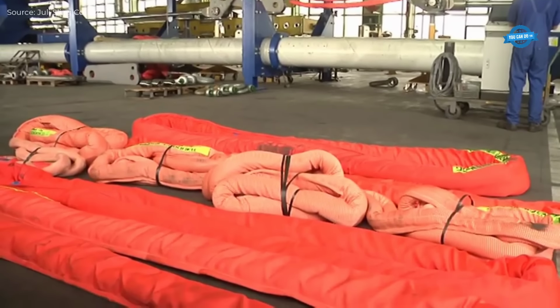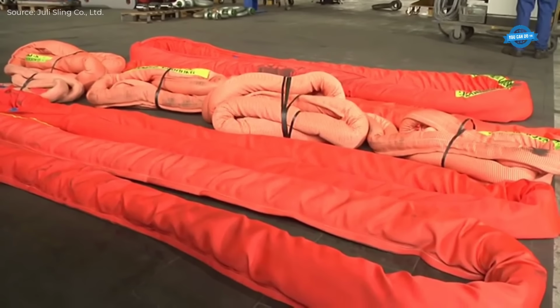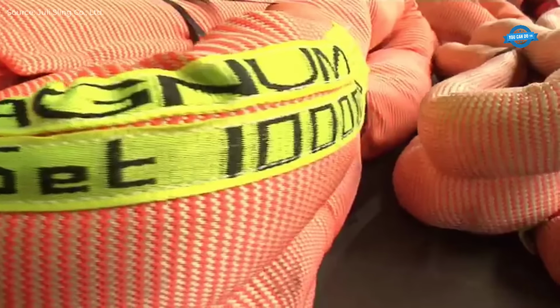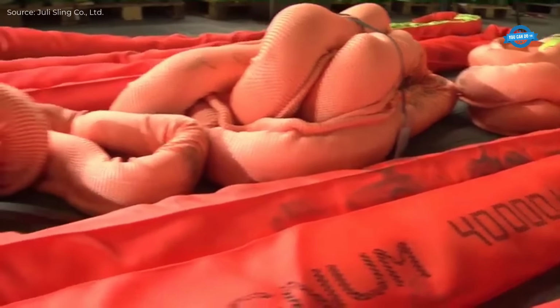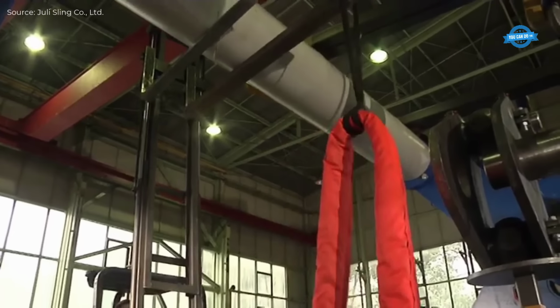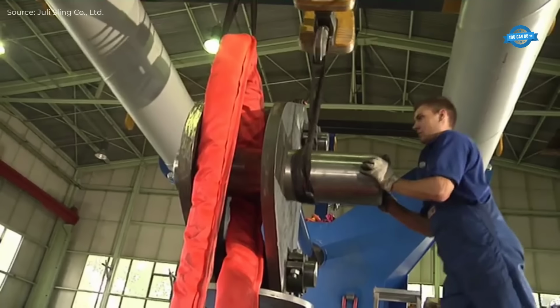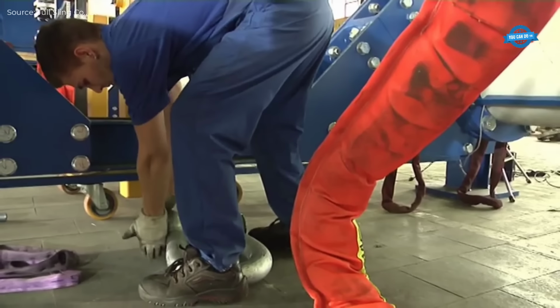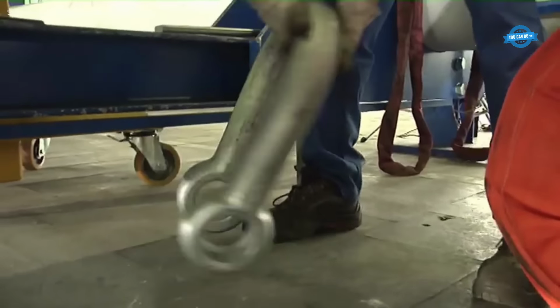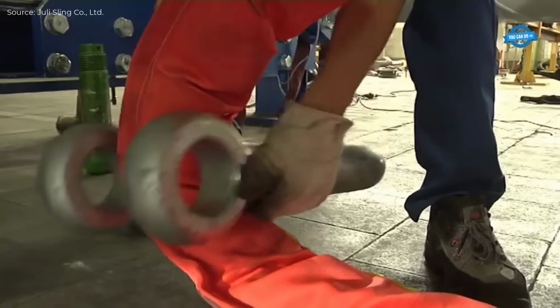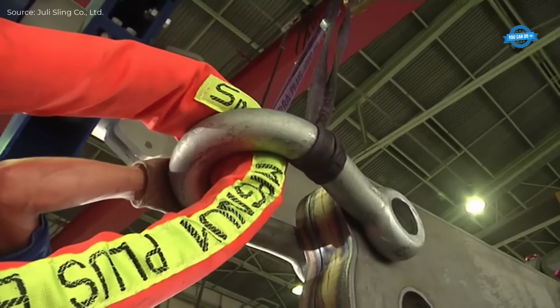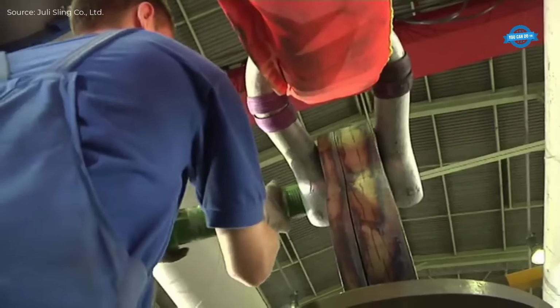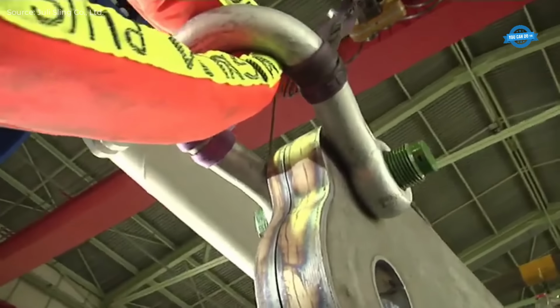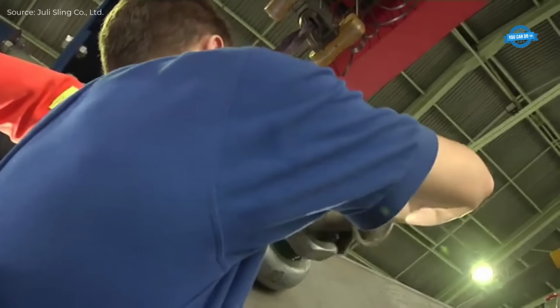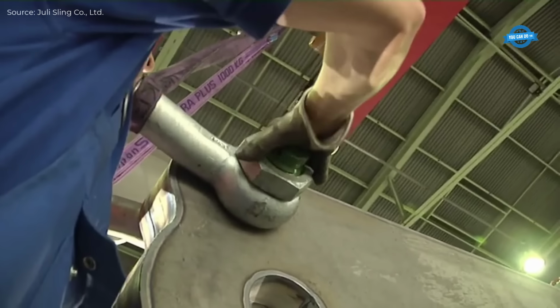The objective was to determine the breaking strengths of specific round sling and shackle combinations. Four round sling shackle combinations were tested, with rated load capacities of less than 10 tons and more than 10 tons. For load capacities under 10 tons, the breaking strength was defined as 5 times the rated load, while for capacities greater than 10 tons, the breaking strength was set at 4 times the rated load. The force was applied gradually during the tests, ensuring that it remained consistent to prevent sudden fluctuations or complete failures of the sling. In addition to static load tests, variable load tests were conducted, where the same part of the sling was subjected to cyclic loading to simulate real-world use.